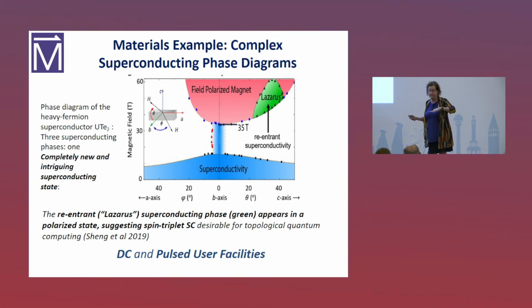And what was found was that, as many of you know, I'm not going to be giving a public lecture, I'm going to assume you know what a superconductor is, that if you apply a field to a superconductor, you break the superconductivity. So we have here, as a function of angle in the uranium tellurium-2, if you apply a certain field, this white area is where it's not superconducting anymore. Okay? What's interesting at this angle, the superconductivity lasts up to 35 Tesla.